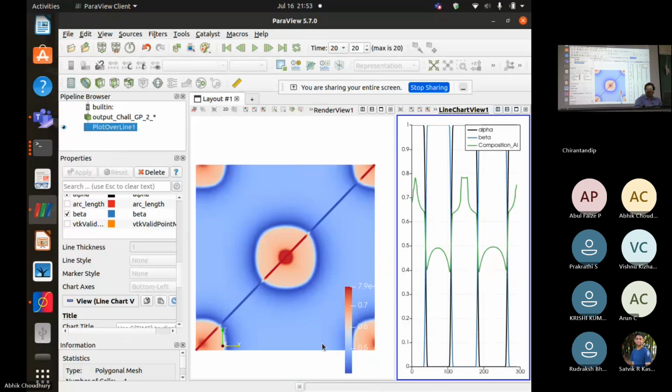Because solid diffusivity is 0, anything that is in the solid will not evolve with time. It is frozen. And that's why segregation is important. In that classical experiment also, when you are solidifying, it will retain all the solidification history in the dendrite, and that will be frozen in time. That is essentially what is happening in the simulation as well.